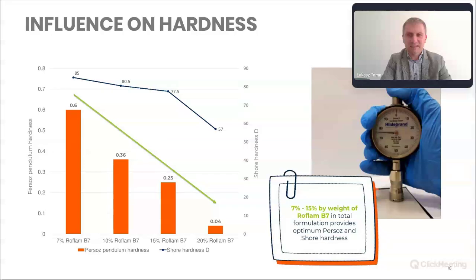Also, we see that hardness can correlate to some extent with the Young modulus and tensile strength parameters. Again, we see good results from 7 up to 15% of the Persoz pendulum hardness and Shore hardness. And if we increase this concentration up to 20%, these parameters also drop very sharply, and the film becomes plastic.